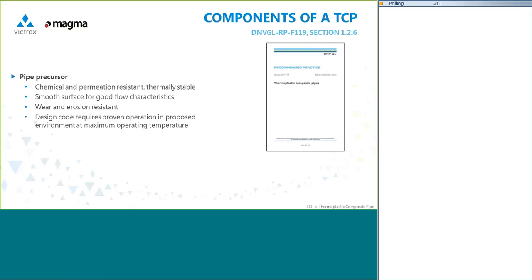This is the inner part of the construction, and it bears actually no significant part in the overall strength of the pipe itself. Its main function is to act as a chemically and permeation resistant barrier. Ideally, it will have a very smooth surface and provide improved flow characteristics for the diameter of the pipe. And of course, it should be wear and erosion resistant, because you want that smooth surface to remain for as long as possible. The design code is quite explicit in how liner materials need to be tested. And specifically, it requires that the liner must have proven operational capability at the maximum operating temperature.